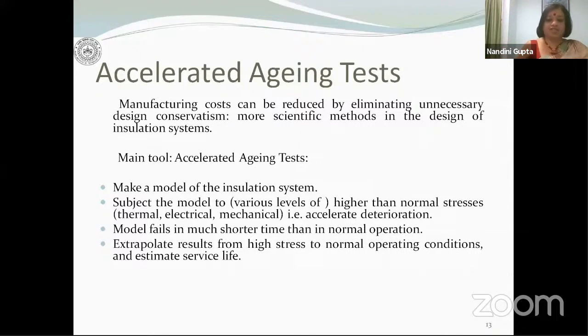Once you accelerate the deterioration process, what is expected is that the failure mechanism will work faster than in normal conditions, and therefore failure will occur in a shorter time than in normal operation. This is not always that straightforward, but I'll come to that point later. So once you have the data over short periods of time, you will have to extrapolate these results from high stresses to normal operating conditions and estimate the service life.